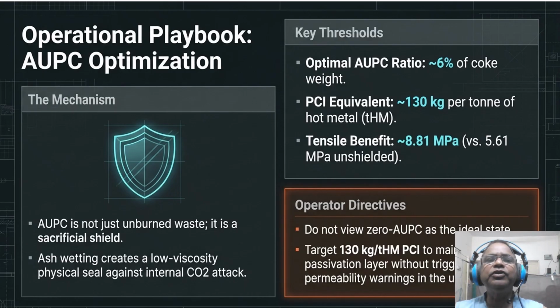So do not view a zero AUPC state as the ideal. We need to target that 130 kg per ton hot metal PCI rate to maintain that protective passivation layer without triggering those permeability alarms in the upper shaft. So it's a balancing act, but now you have the math to win it.